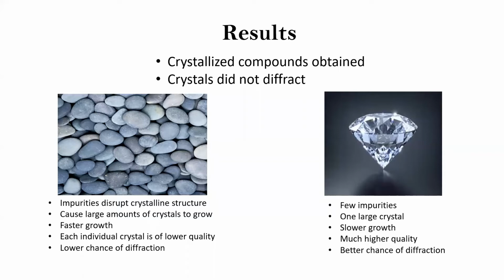Impurities can cause large amounts of crystals to grow, but each individual crystal will be of much lower quality, while a good crystal will be a singular crystal of much higher quality. Some of you may have thought that having a lot of crystals was a good thing, but that is not actually the case. You generally want to aim for having one defined crystal with an excellent crystalline structure. Bad crystals also grow much faster than good crystals, but have a much lower chance to diffract when analyzed. Next slide, please.